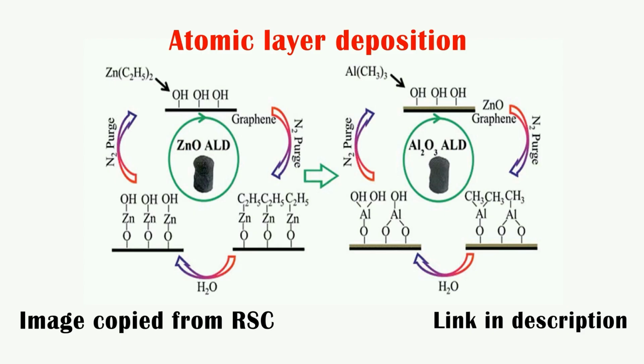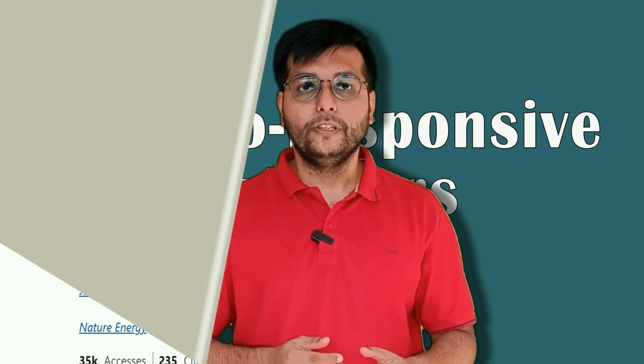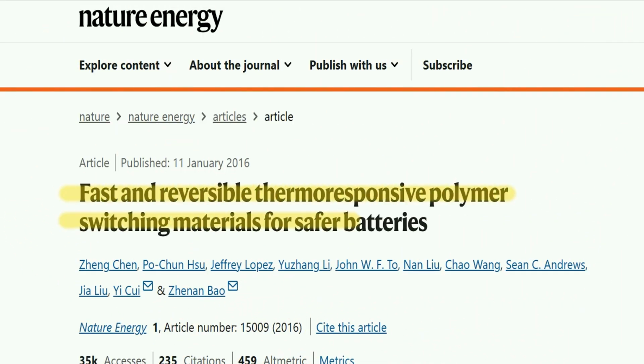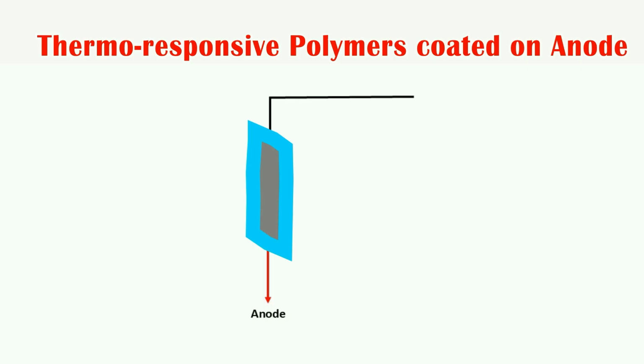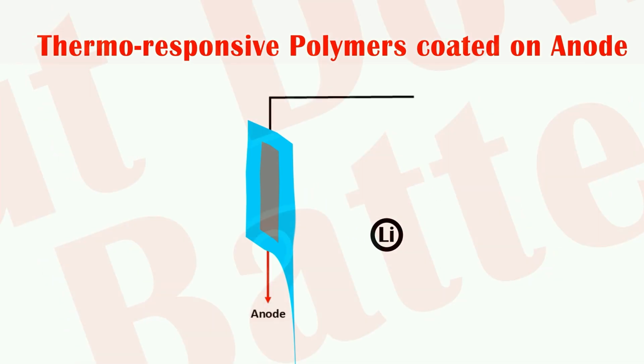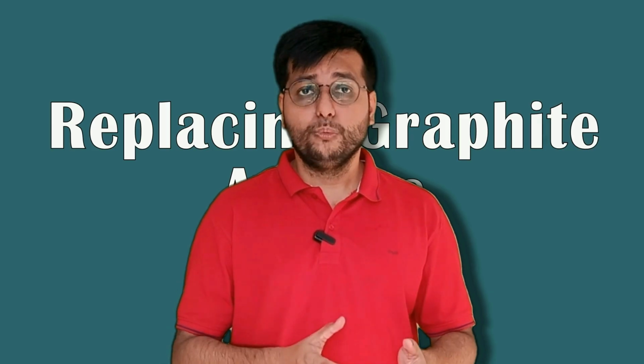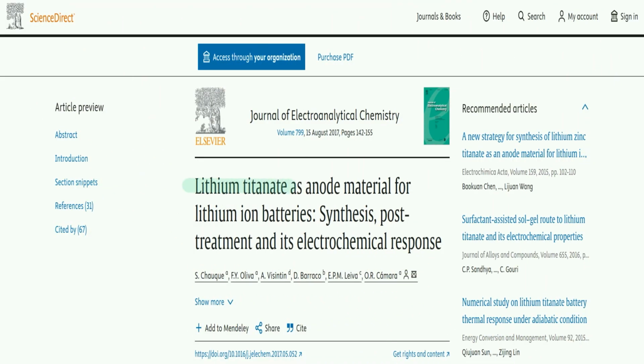In order to achieve this, artificial SEIs are made on the graphite anode, such as through the atomic layer deposition of alumina on the graphite anode. This shows better thermal stability of the graphite anode. In recent cases, thermal responsive polymers are also coated on the graphite anode. This is because when the internal temperature of the battery exceeds a certain level, the polymers melt and form a non-conductive barrier to the lithium-ion transportation to the graphite anode, resulting in shutdown of the battery. In most recent cases, the graphite anodes are also being replaced by other anode materials like lithium titanate, and this shows much better thermal stability than ordinary graphite anode lithium-ion batteries.